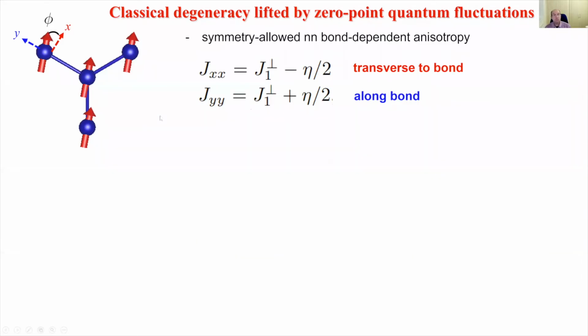So let's consider that on the nearest neighbor bonds, we have different exchange interactions for the spin components that are along the bonds and perpendicular. This is certainly allowed by symmetry. So in other words, we have an eta term here that is non-zero. Now, at the mean field level, the ground state doesn't depend on the orientation of the spin's phi with respect to some reference direction, but the spin wave spectrum would depend on phi.